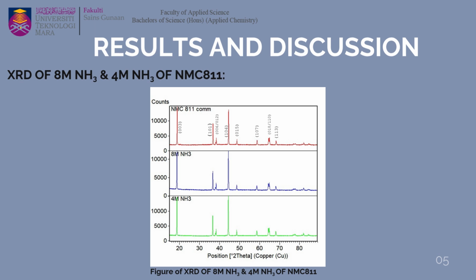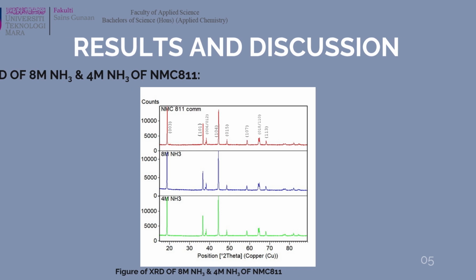concentration affects synthesis quality. So ammonia acts as a complexing agent and the pH controller. The 8 molar ammonia concentration achieved the target pH faster and with a smaller volume, promoting quicker precipitation. In contrast, the 4 molar ammonia solution requires a larger volume and results in slower nucleation and crystal growth, which can promote better control and reduce cation mixing.